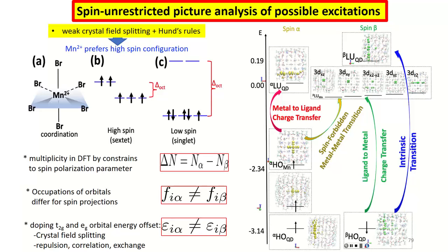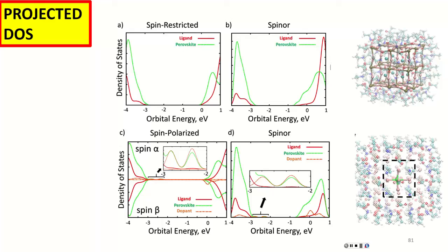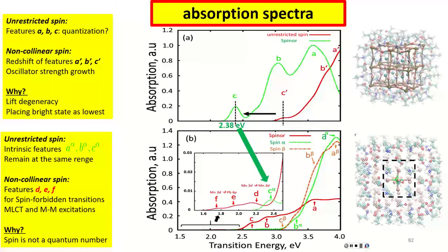If you are restricted to unrestricted DFT, then your absorption and emission will be absent of the spin flip transition, but you can at least consider the density of excited states corresponding to spin flip transitions and show that they are at the right energy. And with spin orbit, these spin forbidden transitions come to the redder part of the spectrum, and that is what is expected to give larger photoluminescence.